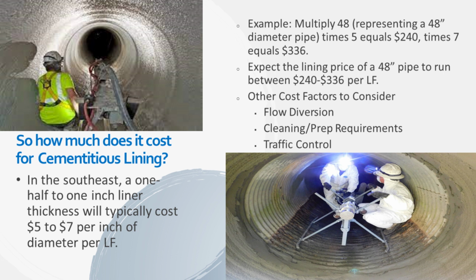And this is a formula that I came up with. It works pretty well here in the Southeast. You may need to adjust it in your area, but it represents the pricing here in the Southeast pretty well. And here's the example. You see it on the screen there. A 1/2 to 1 inch liner thickness will typically cost $5 to $7 per inch of diameter per linear foot.